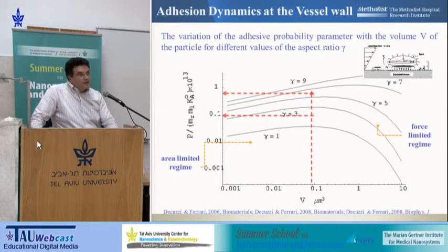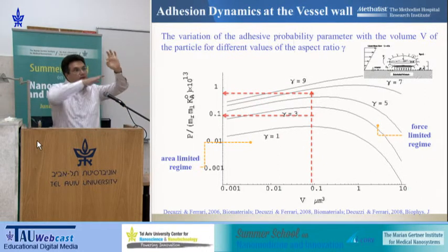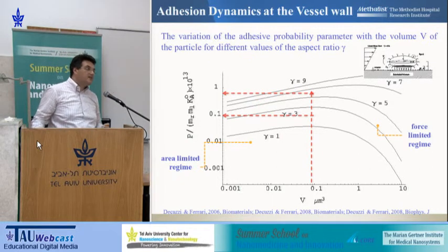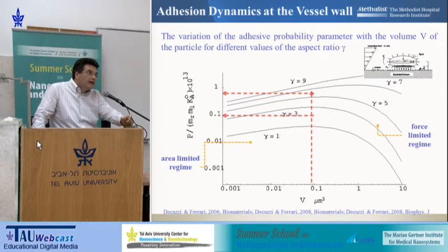And this is easy to understand. If you have a discoidal particle, the surface of adhesion of the discoidal particles with the vessel walls is much larger than the surface of adhesion of a spherical particle, which nominally is one single point. Right? You have a spherical particle sitting on a flat geometry. The contact between the particle and the geometry is a single point. If you have a discoidal particle with a major base, a circular base, you have multiple points of contact, which means multiple ligand and receptor bonds that can be generated simultaneously. So a stronger adhesion that you can actually achieve. And so, again, this is the reason why we're looking and using discoidal particles.